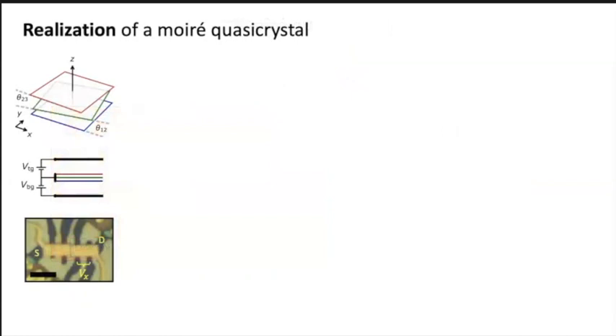So in order to do this, what we did is what I just mentioned. We build three layers of graphene, we stack them on top of each other, and rather than choosing theta, minus theta for the magic angle alternating twist, we're going to choose theta 1-2, theta 2-3, where theta 1-2 and theta 2-3 are different now, a little bit different. I'll tell you later how different we want it to be or not. So this is the structure.